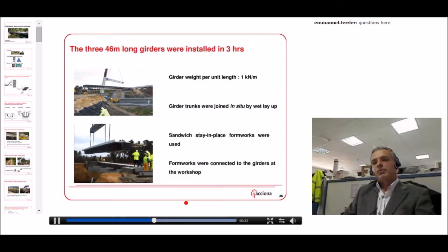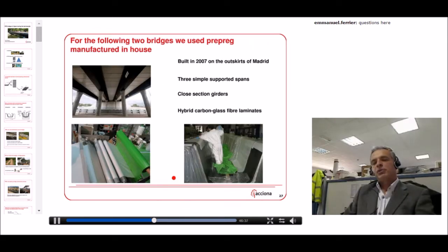For this reason, when we started designing the second and the third bridge, we decided to go for an open section. And why an open section? Because in this case, you can use a steel mold that can be reused for each of the girders. So you can use a couple of molds to manufacture all the girders. In this case, we used 2 molds to manufacture the 24 girders of these 2 bridges.